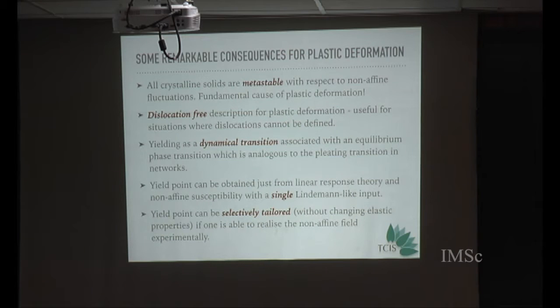So then this plastic deformation is just a dynamical transition associated with this equilibrium transition, and then we don't need dislocations for this description. We can treat it as any other dynamical transition, and the yield point can be got with a single Lindemann-like input, and you can actually selectively tailor this. So I would like to end this part by saying that the fundamental cause of plastic deformation, fracture, basically might be that all crystalline solids are actually metastable with respect to non-affine fluctuations. That is a statement that, we are all friends, and I am making this statement.